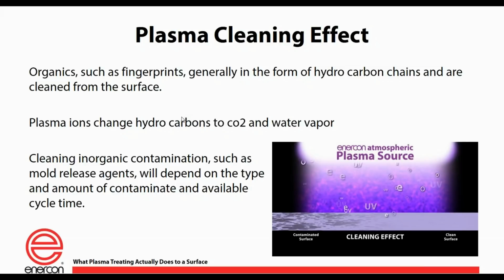Okay, to go back over that, the cleaning effect that we have. There are multiple levels of cleaning that we're going to be doing. The first is removing the static. Anything being held on by the static can be removed. Then you have organic contamination that usually is changed over to CO2 and water vapor. And then you have inorganic. So those are the three things that we're going to be cleaning. The inorganic by far is the toughest, and depending on the level of inorganic contamination, you may or may not be able to use certain surface cleaning techniques, including plasma. So that sometimes will limit what you can do. But in most cases, we can get most of those contaminations off of the surface.